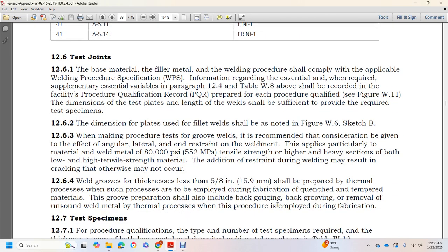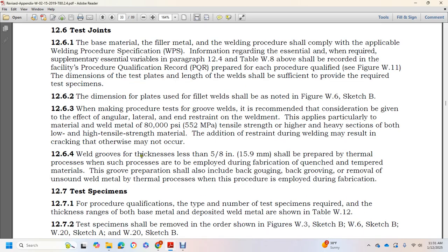When making the procedure test weld for groove welds, it is recommended that consideration be given to the effect of angular, lateral, and end restraint on the weldment. This applies particularly to material of the weldment with 80,000 psi tensile strength or higher, or having sections of lower and higher tensile strength. Additional restraints during welding may result where cracking otherwise may not occur. Weld groove thickness less than 5/8 of an inch should be prepared with a thermal process.